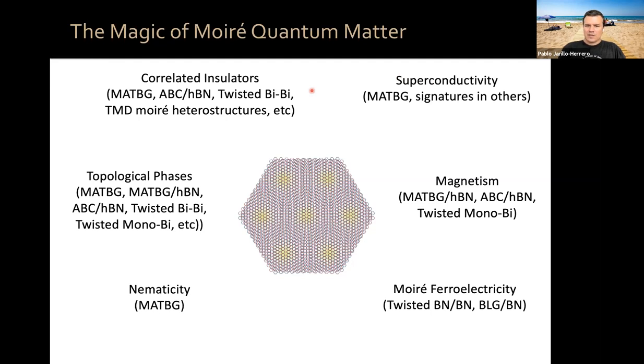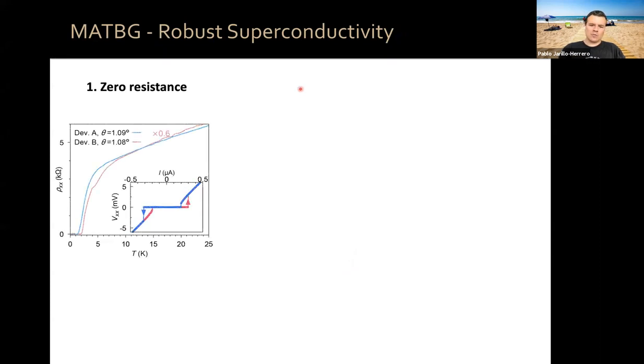And in magic angle twisted bilayer graphene, the bilayer case, robust superconductivity has been seen and reproduced by many groups. What do I mean by robust superconductivity? On one hand, the observation of zero resistance. When you cool down, in these two different devices of magic angle graphene, your resistance goes down linearly, this is strange metal behavior. And then there is a superconducting transition, and the resistance goes down to zero.